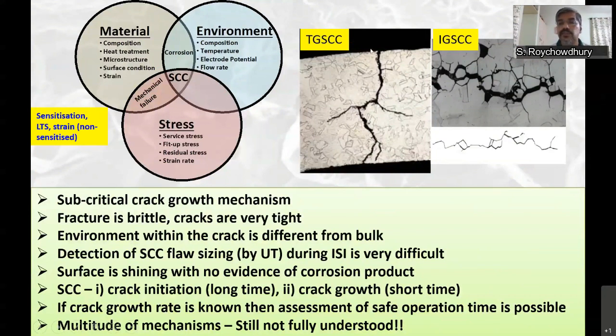What I mean by IGSCC: two modes of cracking. TGSCC is transgranular, where the cracks grow across the grains, and IG means the crack will grow along the grain boundaries. Some features of SCC: it's a subcritical crack growth mechanism. Even if the crack length is less than the critical crack length, it will keep on growing. From a mechanical point of view, as long as the crack is less than the critical crack length and K, the crack driving force, is less than K1C, the fracture toughness, the crack is not supposed to grow. But it can grow due to stress corrosion cracking. So SCC is one of those subcritical crack growth mechanisms.